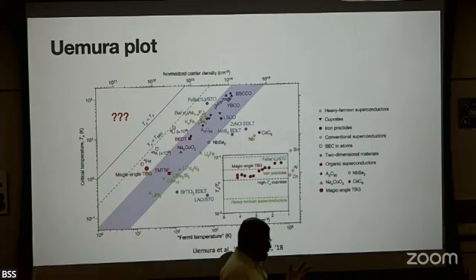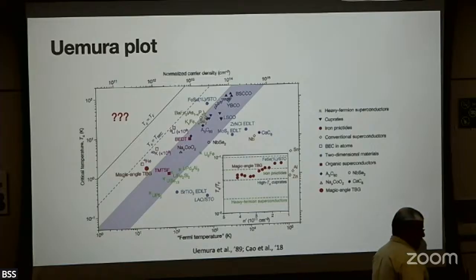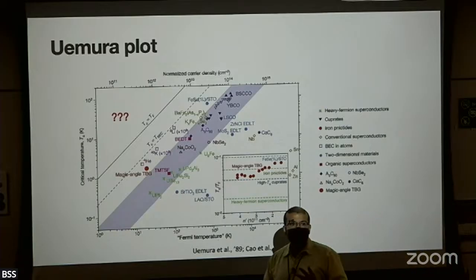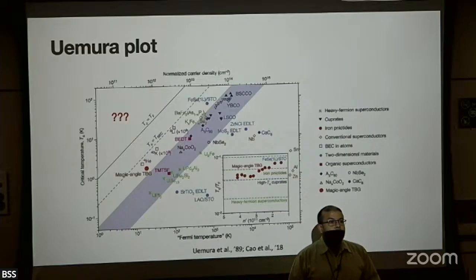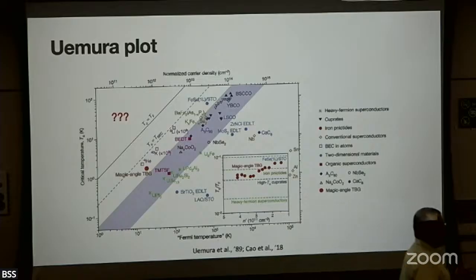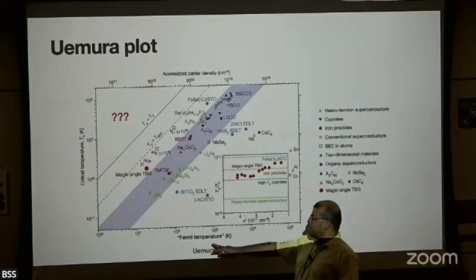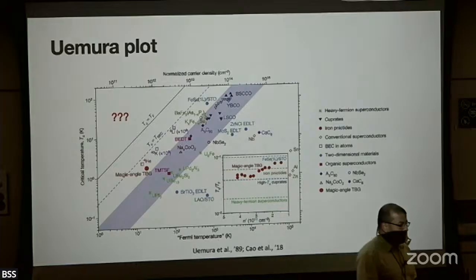Well, you again turn to experiments. And it was pointed out by a very careful analysis that if you look at all superconductors, there does seem to be a wall that you hit. You cannot exceed a superconducting transition temperature that goes above some intrinsic energy scale. Now, what is that intrinsic energy scale? There's a reason I put Fermi temperature in quotes, because extracting a Fermi temperature from an actual measurement is not that straightforward.